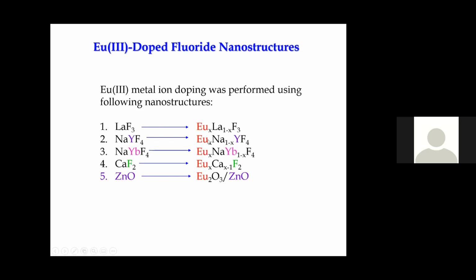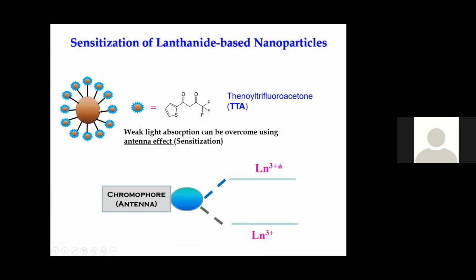So you see, we are working on lanthanides, and these lanthanides can be embedded in different matrices, different materials like lanthanum fluoride, sodium yttrium fluoride, ytterbium fluoride, calcium fluoride, zinc oxide. These are what we call the matrices or the nanoparticle base, and we embed, or in science we dope, europium, which is a lanthanide, to a certain percentage. So the idea is, again, you make the nanoparticle and you coat the surface. We call it surface engineering. We coat the surface with this ligand, which can absorb light. It's a really good absorber, and it will transfer that energy to the lanthanide, so you get the light out.